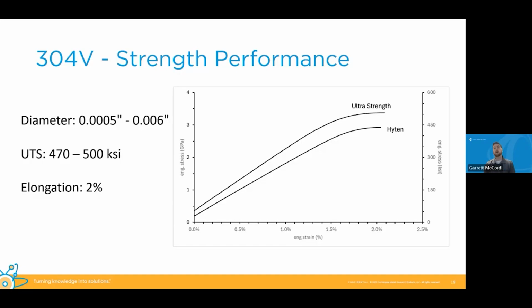To go into the stress strain curve for 304V ultra strength, the difference in strength isn't as drastic as the tungsten is. However, with typical Hyten material, which was our previous highest strength material in 304V, we see about a 30 to 50 KSI jump in tensile strength. The sizes that this is available for is about a half a thou up to 6 thou inches. And we've been able to reach about 500 KSI while still maintaining pretty good ductility of 2%, which is very close to Hyten condition as well.